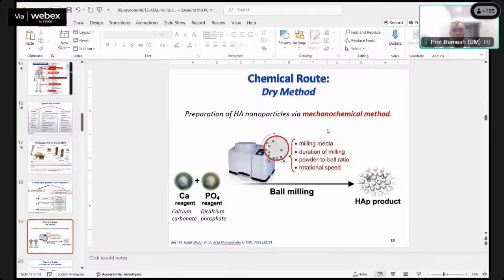So like ball milling or planetary mill, through this milling, a mechanical form, that means rotation. Electrical energy is converted into rotation energy, through some mechanical device which allows the rotation to take place. That allows the chemical reaction between the agents that we use, a calcium agent and a phosphate agent, typically calcium carbonate and dicalcium phosphate. During this mechanochemical process, the byproduct will be hydroxyapatite.